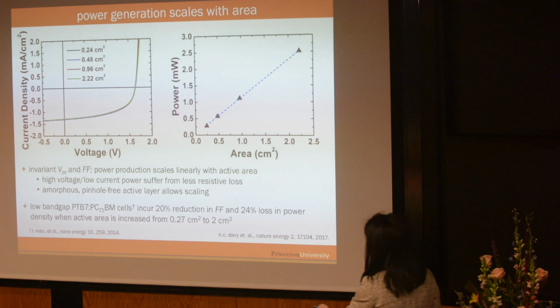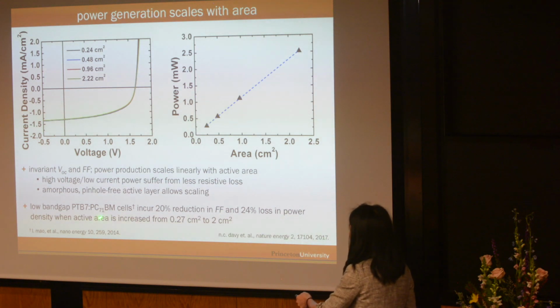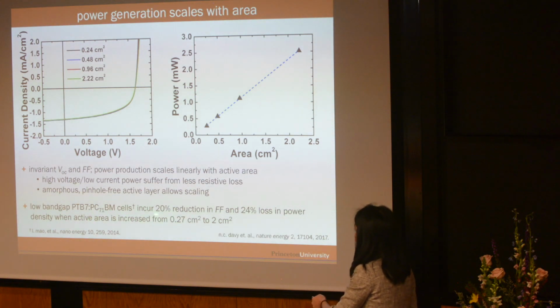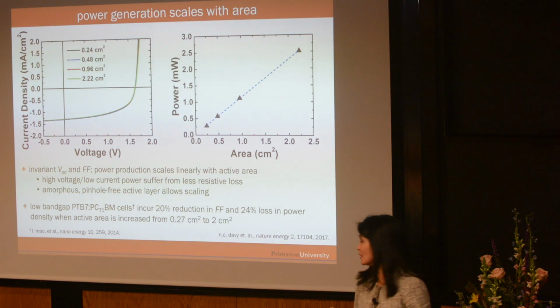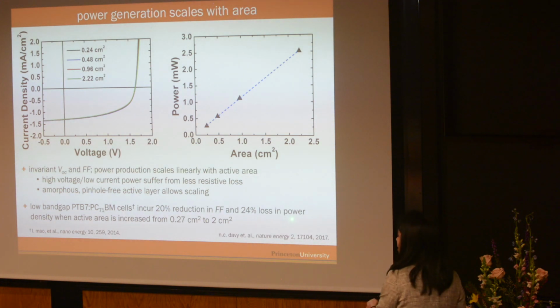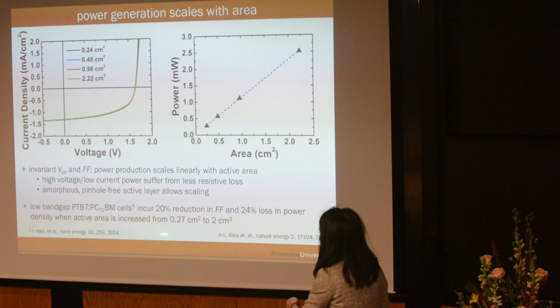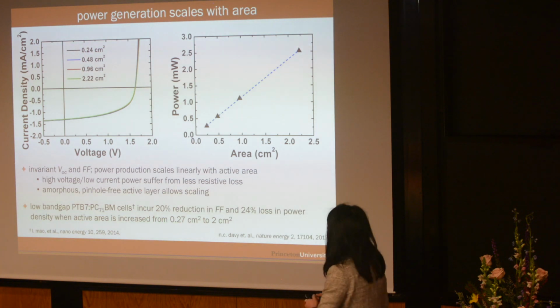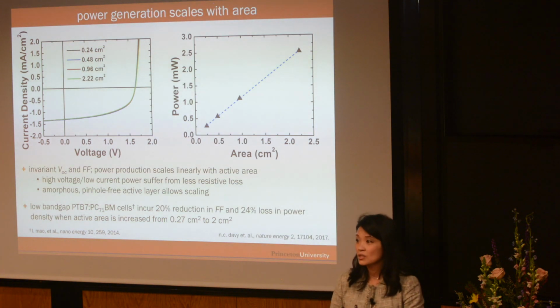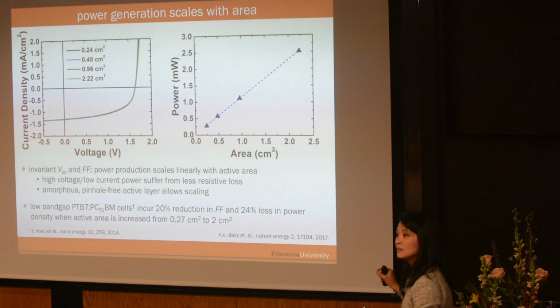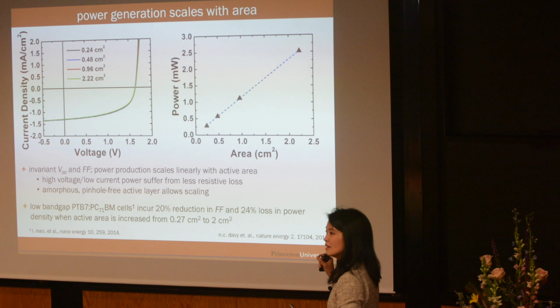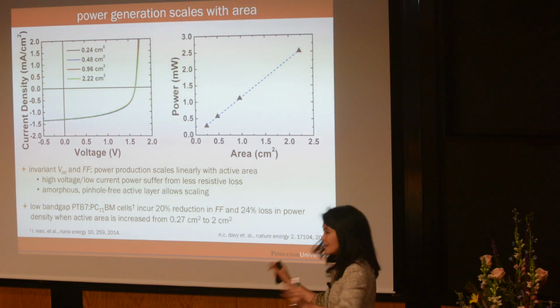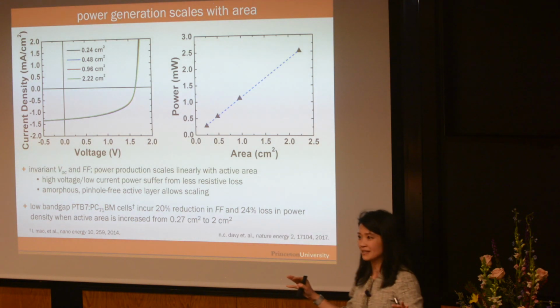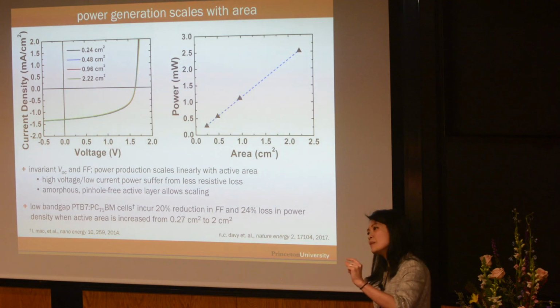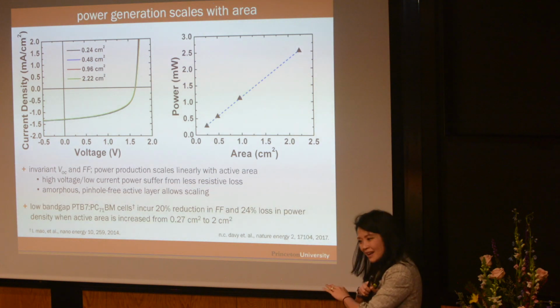So for reference, if you have a low band gap solar cell, and this was reported, they incur a 20% reduction in fill factor, 24% loss in power density when the active areas increase from 0.27 centimeters squared to 2 centimeters squared. So we wanted to circumvent this problem, and we thought, well, the best way to make a pinhole-free layer is to make everything defective, right? It's to make amorphous layers. So we sacrifice a little bit in the charge transport, but now everything's defective.